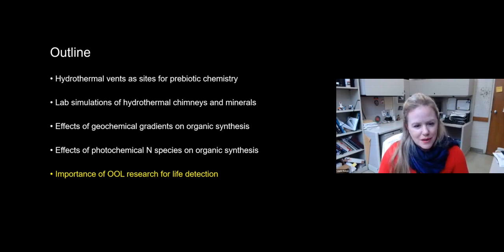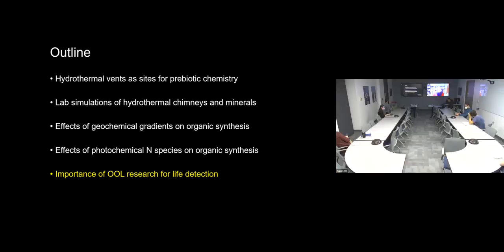Well, we haven't done any modeling on this, but I think that it would be a good idea. So things like what are the kinetics of the nitrite reacting with iron versus the kinetics of iron reducing the organics? Because also in the previous set of experiments with only ammonia, we do see that it seems to take a little longer for the amino acid to form than it does for the reduced product to form. So looking at these kinetics and how that might vary as a function of conditions, especially temperature, I think would be very interesting. Any other questions?